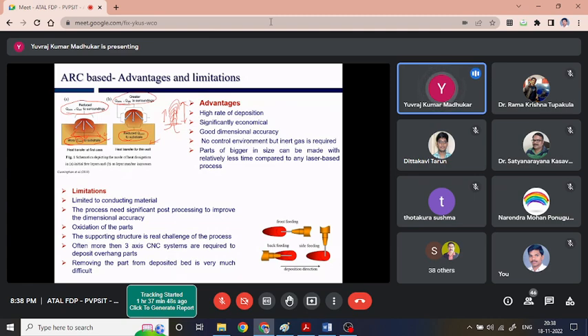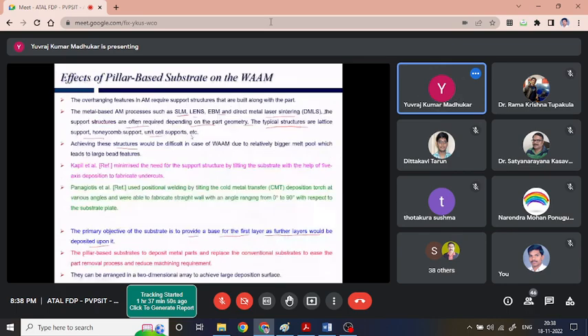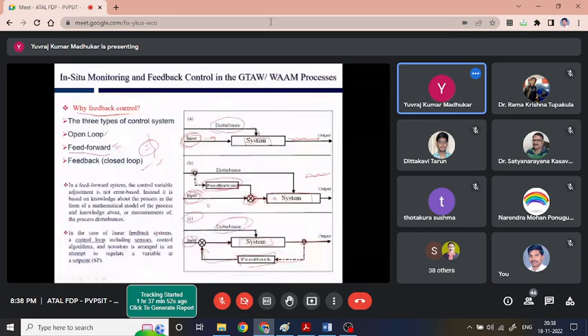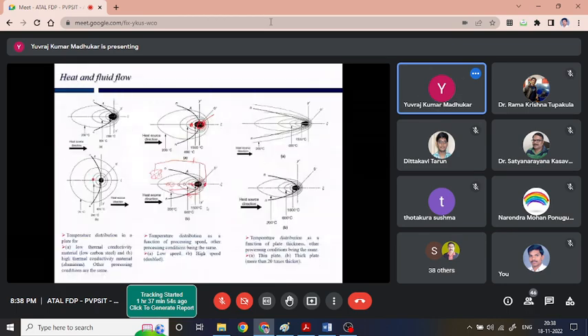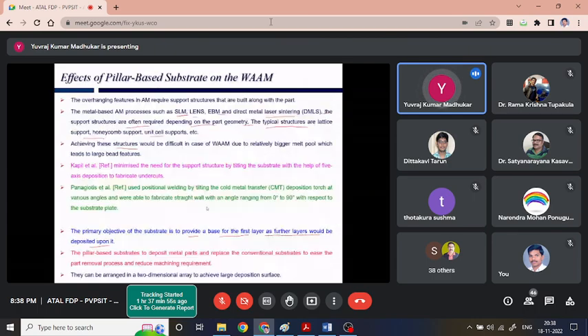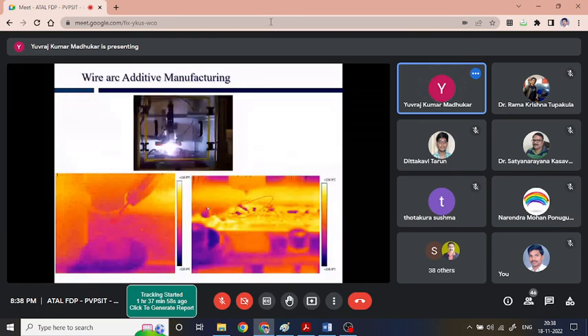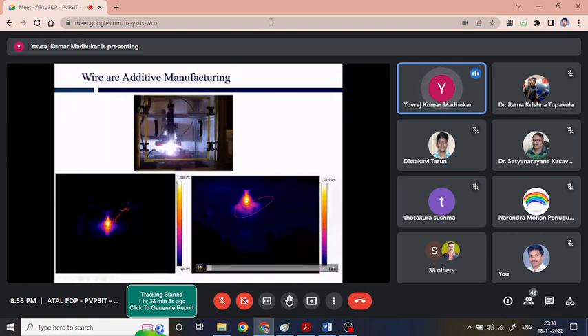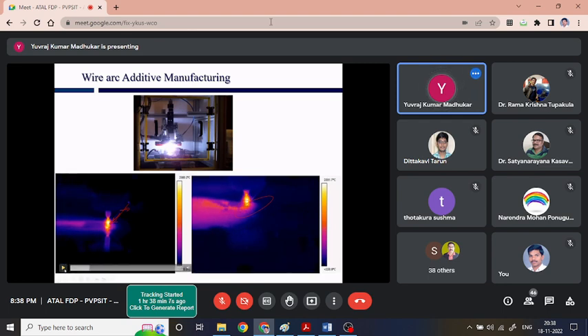That's why, when we saw the thermal profile for the first layer of deposition and then the 10th layer of deposition, without changing the parameters, we could see that for the first layer the build pool size is limited or very small, of the order of hardly 5 to 6 mm, but in this case it is of the order of nearly 15 mm. This is the 10th layer of deposition.